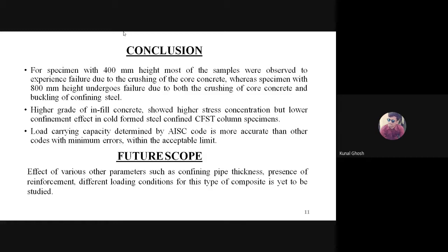Higher grade of infill concrete showed higher stress concentration but lower confinement effect. Load carrying capacity determined by AISC is much more acceptable.